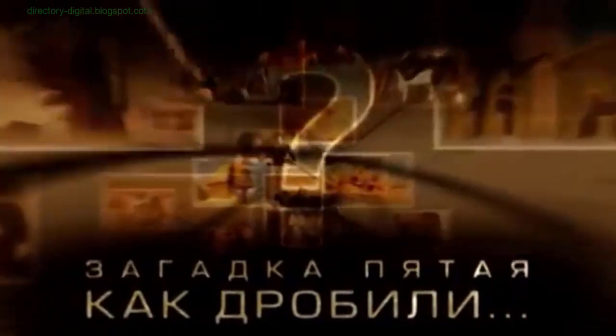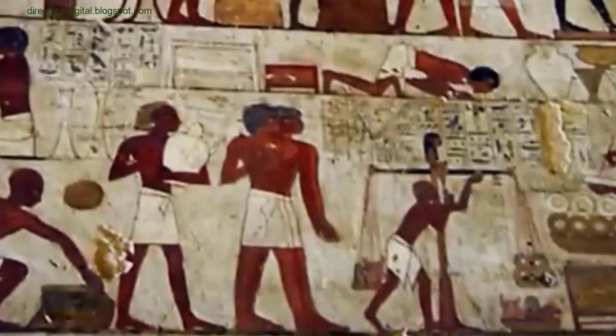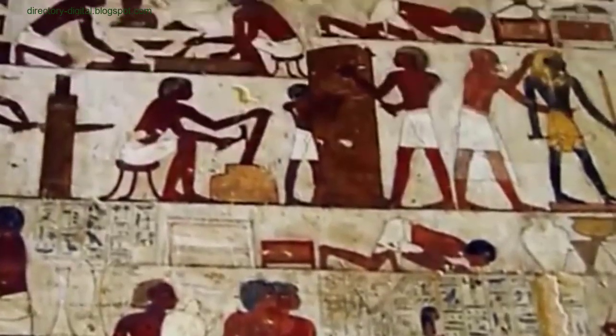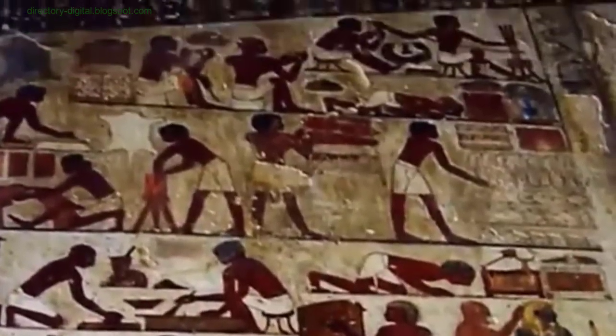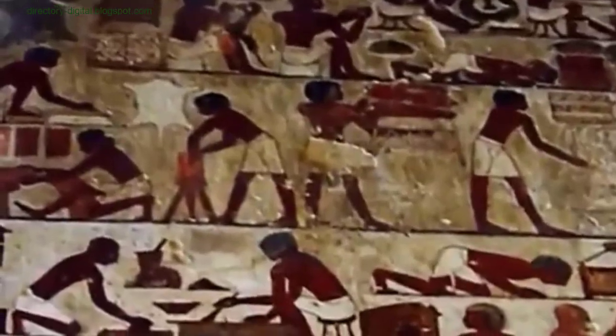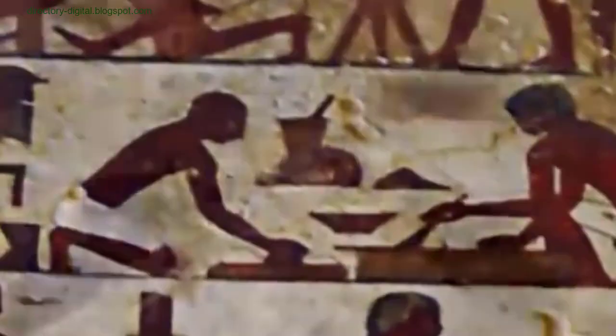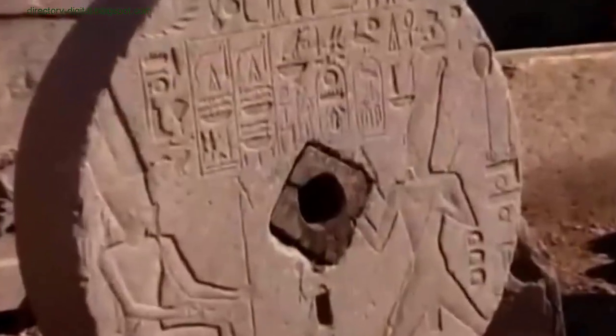The goal was to study the stone's structure and elemental composition. A sample was prepared using a chipping method, followed by the application of an electrically conductive element, carbon, in a vacuum to create a thin carbon film on the sample surface. This prepared sample was then examined using a scanning electron microscope equipped with energy and wave dispersive X-ray detectors, which can determine elemental content with high accuracy.